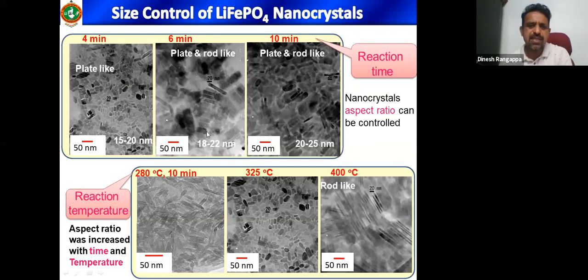So we can systematically control the size and morphology of lithium iron phosphate by controlling the reaction time and reaction temperature. From plate-like to rod-like morphology, we could obtain by controlling the reaction time from 4 minutes to 10 minutes. Similarly, from 280 degrees centigrade to 400 degrees, we can control the morphology, rod-like and plate-like.